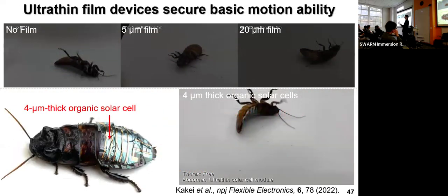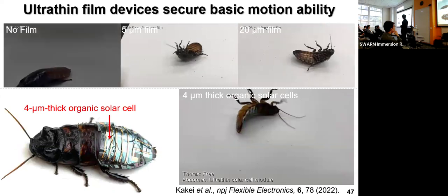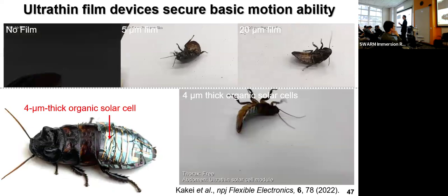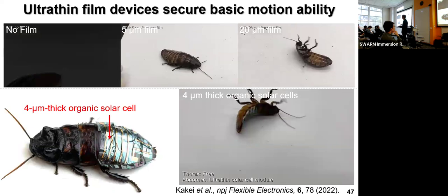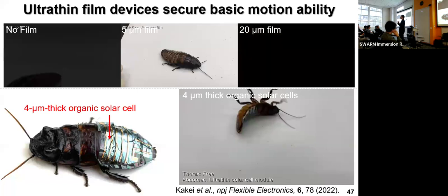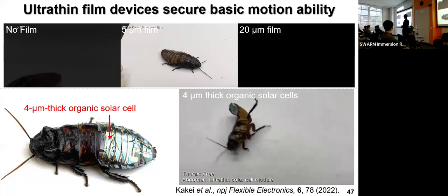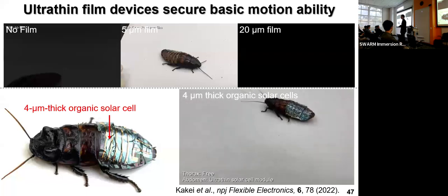And then the next trial is the self-righting attempt. Here, these top 3 movies show the attempts of self-righting, the upside-down attempt, with no film, 5-micron film, and 20-micron film. With no film, they quickly succeed. With 5-micron, it takes time, but finally they succeed. With 20-micron, they cannot. We humans almost don't recognize the differences between no film, 5-micron, and 20 microns. All are thin enough for us. But for them, this is a very critical difference. And then fortunately, our solar cell is 4 microns thick. So they succeeded almost 100% of the attempts.